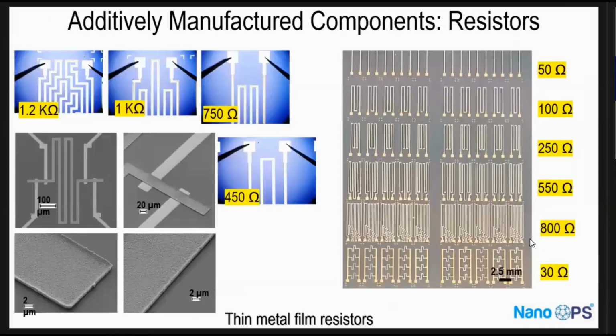Okay, so this is a project with the Air Force, and this is fully printed passive components. In this case, we wanted to print resistors. So the first step we did is we used the resistor ink that you can buy from a lot of the ink vendors for inkjet and so forth. We ran into a problem right away because the ink is basically carbon black with some ceramics, and the tolerance was very, very large. So you cannot print devices that are repeatable, and the devices have different resistance.